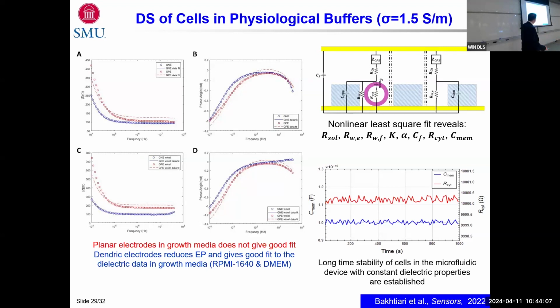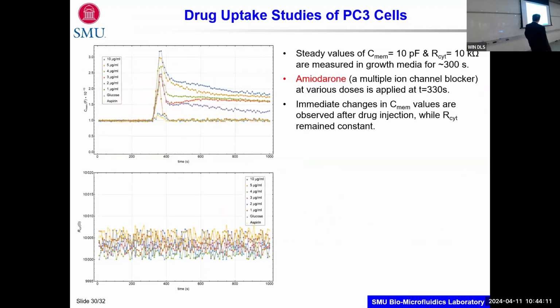So what we then did is that we started to look into drug uptake studies for PC3 cells. Now, of course, my background is pretty thin here, so please don't challenge me on biology. All right, but if you do that, maybe you'll teach me a lesson too. What we did is we used amiodarone, which is a multiple ion channel blocker. We first capture the cells, and then we measure the dielectric properties. We see that there is no change in cytoplasm resistance. And by the way, the number here is 10,000. This is 10,005, so it's all constant data, and this is cytoplasm resistance. But the more important thing is, of course, the capacitance values. So we go with different doses of amiodarone, and you can actually see an immediate response.